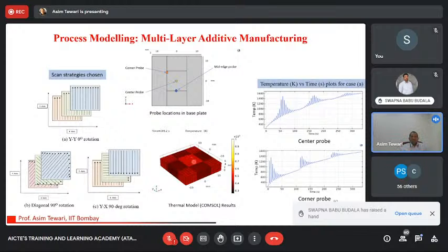So these are some of the leading algorithms which we use, which is a combination of eigenstrains for solid mechanics, phase transformations, and heat transfer. So all of the solid state phase transformation and liquid state phase transformation. And all of this put together leads to a clearer understanding of how the residual stresses are being formed. Can they lead to distortions and can they lead to cracking? And this can be used to optimize the additive manufacturing process, because it's an open question.